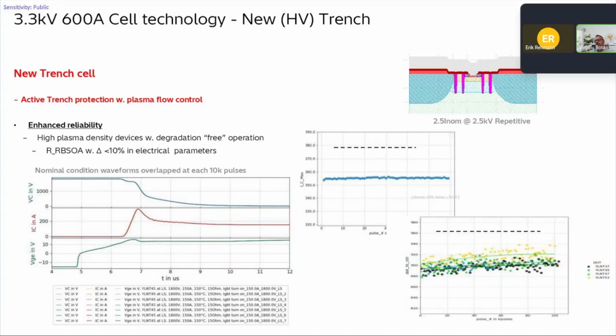Because what happens, of course, is if we would possibly see a degradation of the gate dielectric, especially at the bottom of the trench, we would get a change in the gate dielectric, and through that the capacitances change, and there is a change in how the IGBT turns on and in the di/dt. Of course, per se, that is not immediately dangerous, but it puts more stress over time on the diode, and in the end can lead to failure.